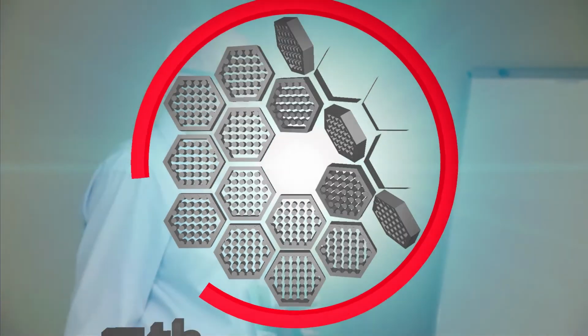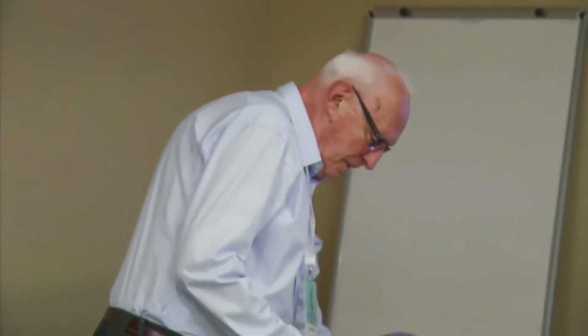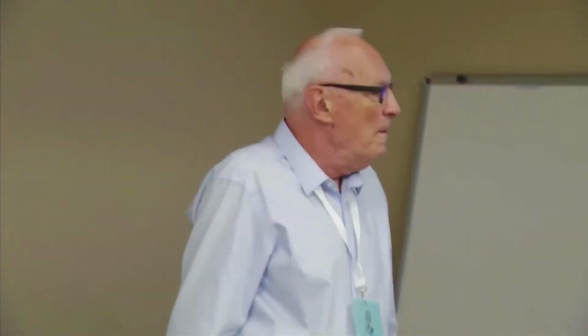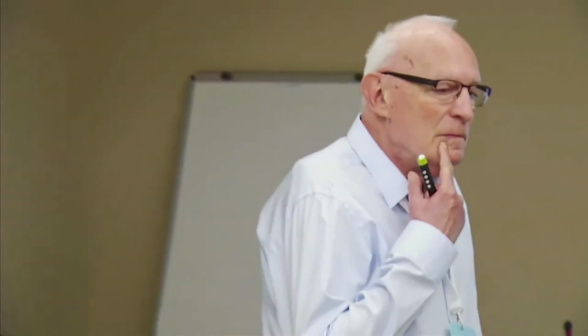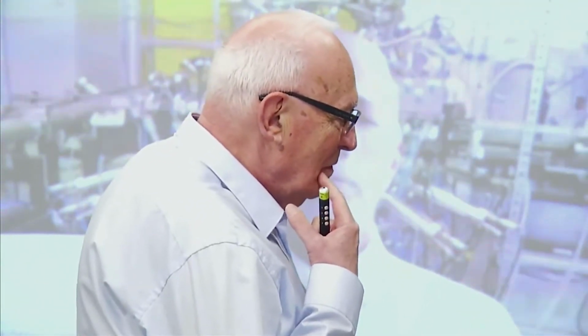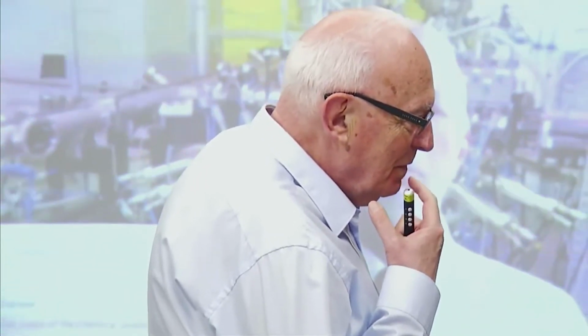Maybe some other results. Excuse me, I have a question if I may ask. So there has been a relatively old paper from 1997 from Fujimori when they have been making low-level photoemission measurements, and they have been showing for LSCO that this Fermi energy shift, chemical potential shift in the underdoped samples was actually constant. Did not depend on the hole doping with respect to the undoped samples, and in the overdoped regime it changed.